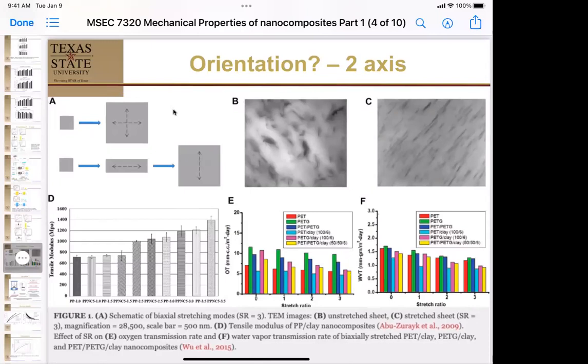From your experience, when you see the one on the C, and then, let's say, a 45 degree angle, where's the most strength? Is it perpendicular to the cellulose or fibers? Interesting. It depends on the nature of the filler. In this case, we're using clays, and the clays are actually on edge this way. So everything in the elongated axis, the XY axis of the clay, is going to give you the strongest tensile strength. But flexural is going to be across that grain, and permeation is going to be across that. Now, if these were fibers, then all we see is an improvement in tensile, with almost no flexural improvement, because fibers are thin. They don't help as much with flexural. That makes sense? Yes.